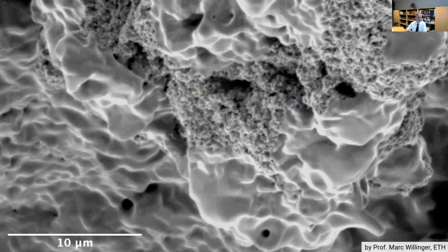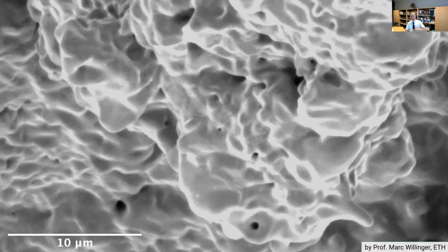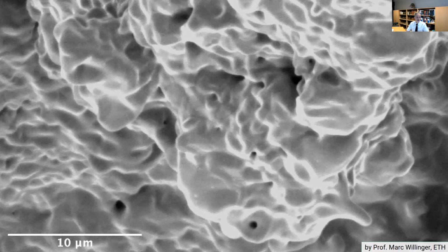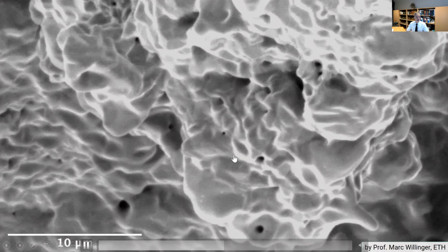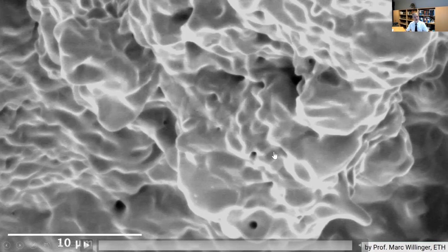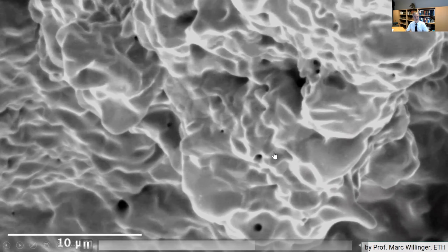And here's a very nice online movie from our colleague and friend, Professor Marc Willinger, also a former Max Planck colleague from the Fritz Haber. And he did a very nice in situ experiment where he put a little piece of such an ore pellet into an electron microscope, which he then flooded in a defined way with hydrogen. And look what happens. You see here this rough and coarse surface of this iron ore. And then during the reduction, as the hydrogen-based reduction goes on, if I play this again, you see that this iron is then starting to cover the oxide beneath it.